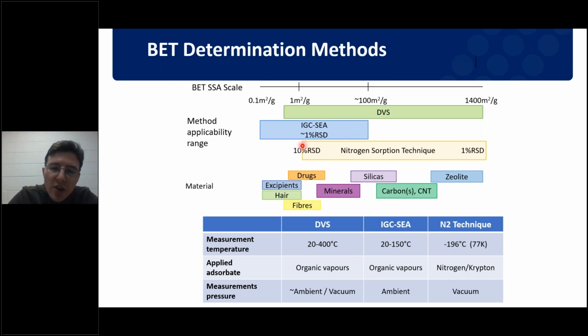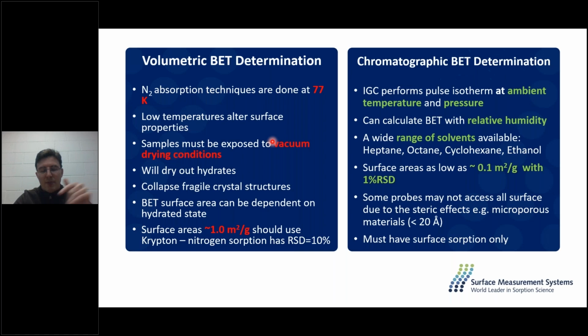Another thing I'd like to highlight is the performance of these techniques for low surface area materials. The nitrogen adsorption technique really begins to fail when you get to 1 square meter per gram and lower. This has a very high relative standard deviation of 10% for this low end of surface area. You have to mitigate that by using something like a heavier noble gas like argon or krypton in order for this relative standard deviation to decrease. Now, inverse gas chromatography excels in this range. We have as low as a 1% relative standard deviation for very low surface area materials. So it outperforms a volumetric technique when doing low end measurement.